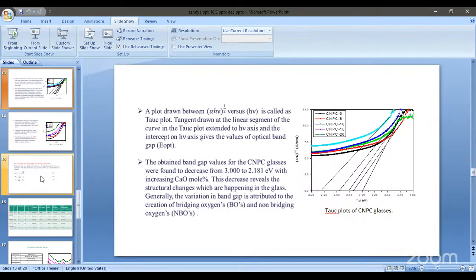Here the optical band gap values of the CNPC decrease, from 3 to 2.181 eV, with increasing CaO mole percentage. And the decrease reveals the structural changes which are happening in the glasses.